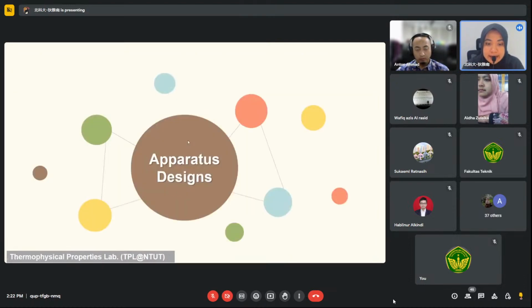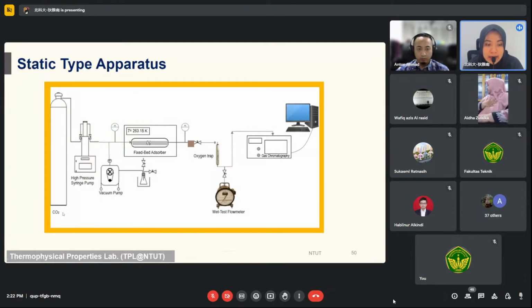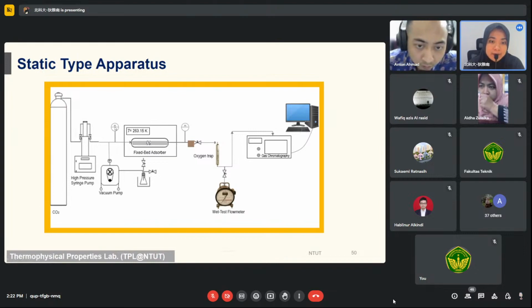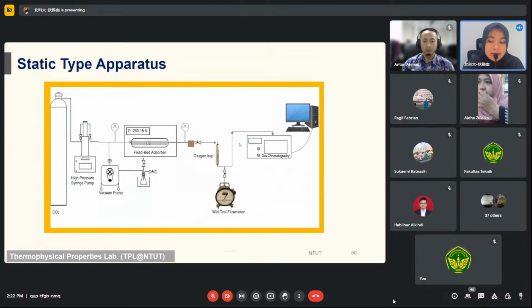So for the apparatus design, we use a CO2 high pressure syringe pump. Here we have the fixed bed adsorber. We just inject or put the sample inside and control the temperature. We also have an oxygen trap to remove the moisture. Here we have the PI, or pressure indicator. Once the inlet and outlet are equal, it means it has already reached equilibrium, and we can take some sample to measure the flow rate and to check the composition of the CO2 absorbed in the system. If the pressure is still not the same, it means it has not reached equilibrium.